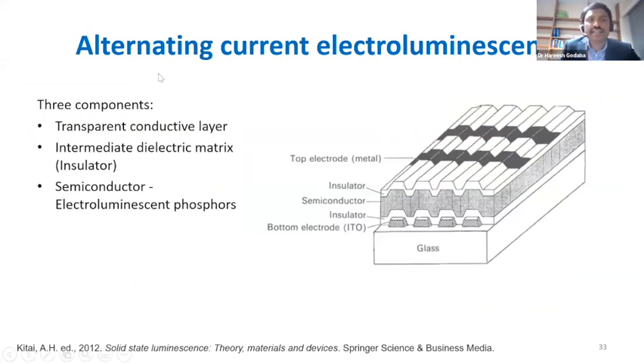So firstly, these are the main components of an alternating current electroluminescent display. These are also like dielectric elastomers in a way. They're basically a dielectric with phosphorescent or semiconductor particles. So these phosphors are semiconductor particles, and then we need to have electrodes on both sides. And then when you apply an AC voltage across these two electrodes, light is emitted from the semiconductor region. Of course, for the light to transmit to the viewer, we need to have a transparent conductive layer, right? So the conductive layer has to be transparent. The dielectric matrix also needs to be transparent, and it needs to be an insulator. And then we need some semiconductor or electroluminescent particles that can emit light.